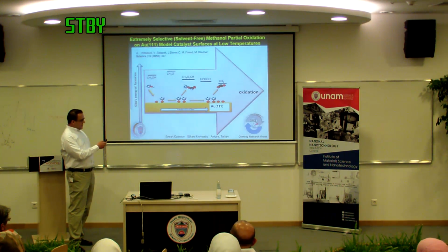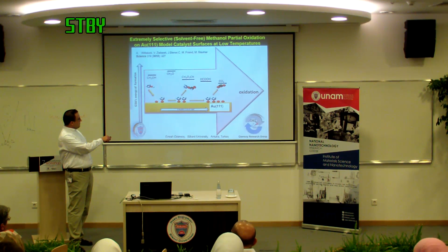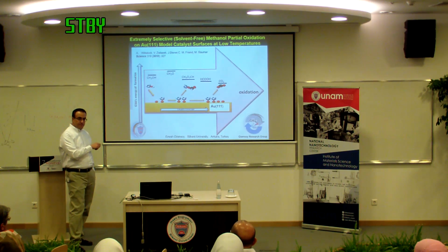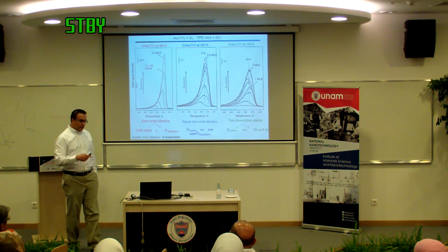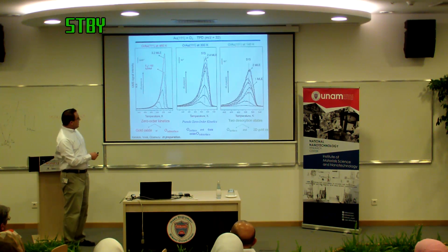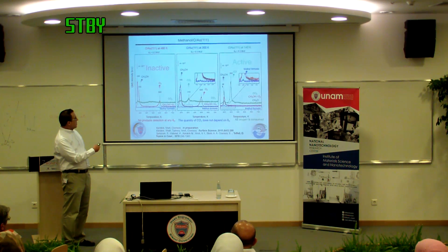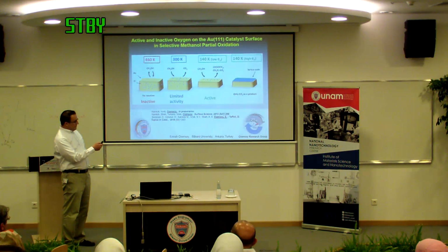So we have been working on this one. The idea was, what is this oxygen doing on the surface? Is it on the surface? Is it in the subsurface? Or is it coming from the bottom? And we've actually verified using mass spectroscopy experiments, generating atomic oxygen using ozone adsorption on gold. I will just cut the story short, we're just going to publish this over the week, so we'll publish. What we verified is that if you generate this subsurface oxygen, atomic oxygen on gold,